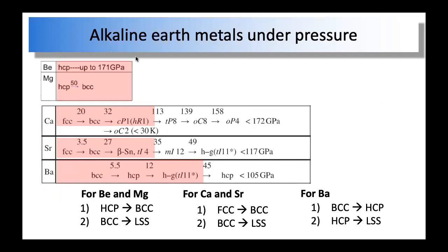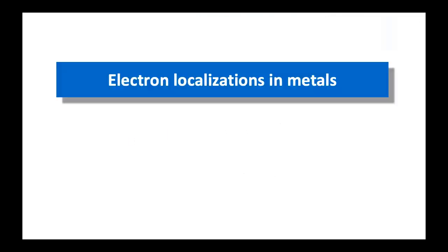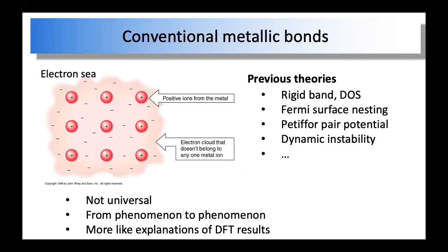And if you look at the alkaline earth metals, that's also very interesting. They all start with close-packed structures, HCP or FCC, but once you compress them, they start to become BCC. Remember, BCC is the stable structure of alkali metals, and it is not close-packed. And then if you further compress them, again they all abandon the simple, high-symmetry structure, and they become structures with open sites and low symmetry. Right, so that's the alkaline earth metals. Okay, so these are the puzzles that we summarize here, and here is the general view that we need to change in order to understand them.